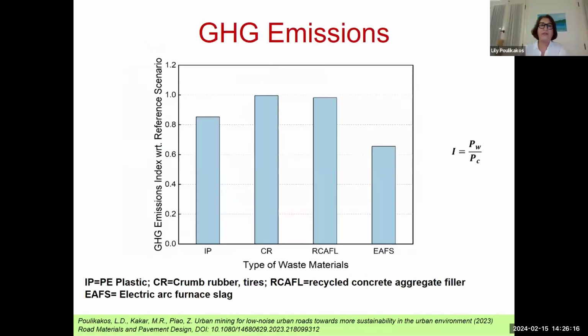So we've gone through this exercise for various types of waste materials. And here is with a certain type of plastic. This is the crumb rubber. This is the recycled concrete aggregate filler and electric arc furnace slag. And we see that introducing again the performance index, it is possible to reduce the greenhouse gas emissions by using alternative materials.